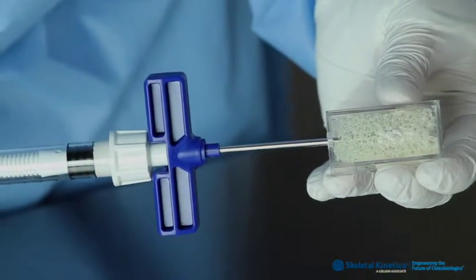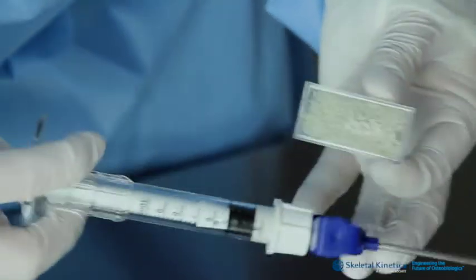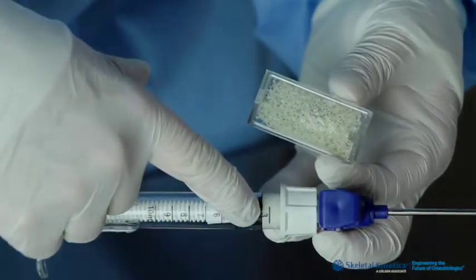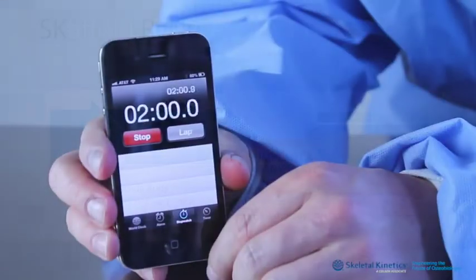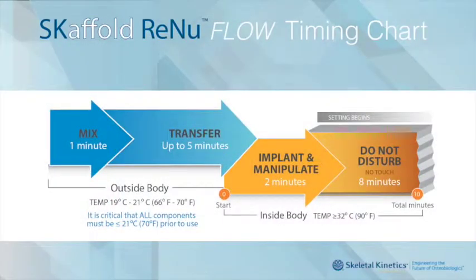The surgeon will have up to 2 minutes to inject, implant, and manipulate the product within the void site. Once this 2 minutes is done, the surgeon should stop manipulation. The product is hardening, and any further manipulation may fail the case. Remember, Renu is crystallizing. If you break the crystal formations, you will compromise the long-term mechanical structure of the product.